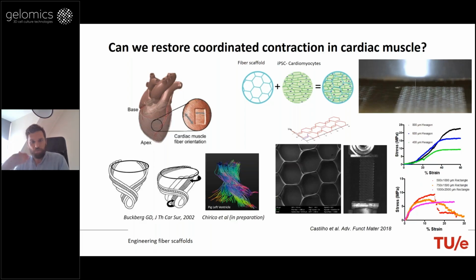So what we did was to keep this bulk material property, but play with the design. By playing with the design, we wanted to achieve the stretchability or the elastic deformation that would allow us to have a patch that could deform elastically within the range that is needed for myocardium repair, so typically between 20 to 30%, and still show elastic behavior without, of course, undergoing permanent deformations. And the hexagons actually allowed us to do that.